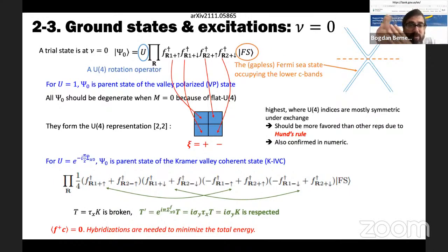For example, this is charge neutrality. I should have 4 electrons in these flat bands, right? They go from -4 to 4. At charge neutrality, which is 0, I have to fill them with 4 electrons. These are the 4 electrons. This is a parent trial state, where the filling is just controlled by the f-electrons. And this is the Fermi sea of this gapless state. Okay, this is the trial state.